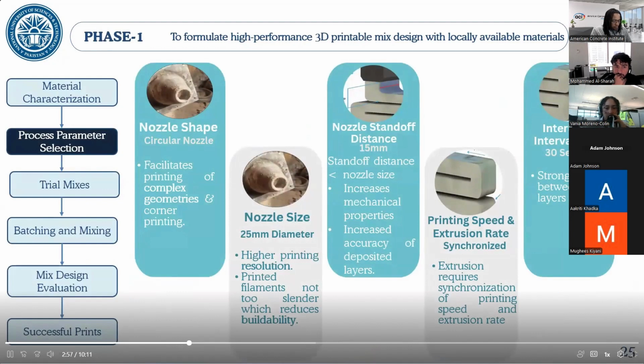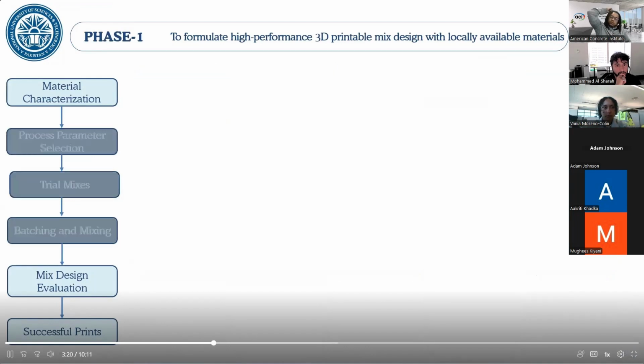Nozzle size was kept at 25 millimeters as it struck a balance between good printing resolution and good printability. Stand-off distance was kept at 15 millimeters, which gave good interlayer stability. Next, print speed and extrusion rate were experimentally kept in sync to avoid breakage or flat elements. And lastly, interlayer interval time was naturally about half a minute due to our short print paths.